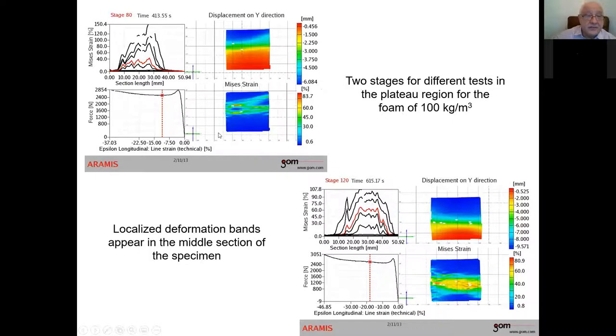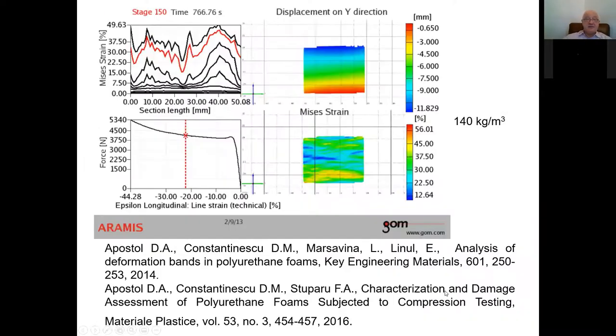These are two different moments, not very far one from the other, but the interesting thing is that the Mises strain in this position looks like this. So you have two different deformation bands, which later on concentrate towards one of them, moving a little bit towards the lower part of the specimen. And again, another situation in which we move a little bit further away. This is another density, and you have this kind of damage and deformation of polyurethane foam. This is a polyurethane.